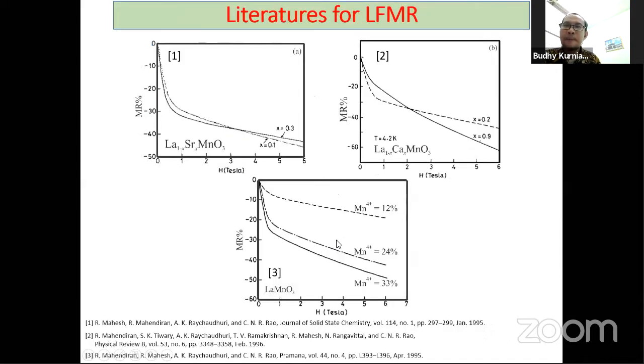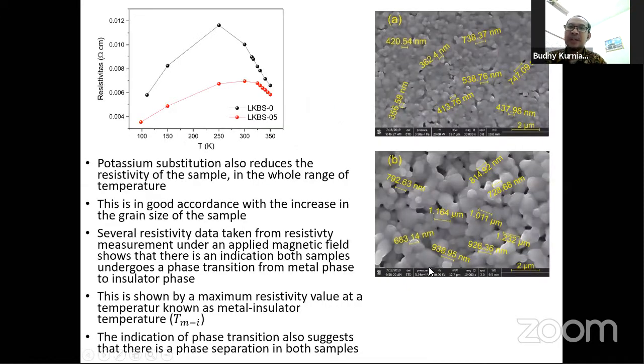This is the picture of the LFMR, same as we can get from our result. And this is some of the experiment from the magnetoresistance phenomena, direct measurement. We collected the resistivity at magnetic field 0, and we find there is a decrease of the resistivity of the sample by adding the potassium content, and this is confirmed with the result of the SEM experiment.